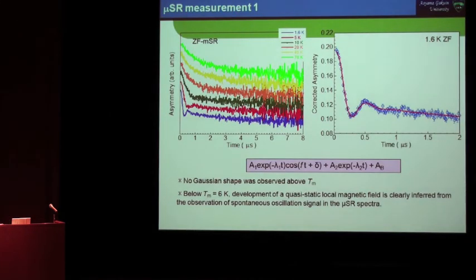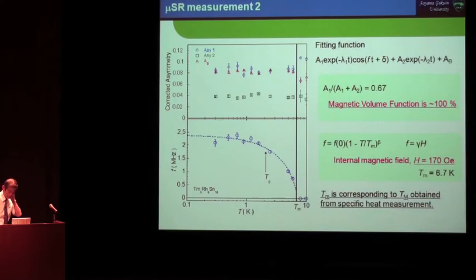So we tried to check the existence of magnetism. We tried to get a μSR measurement. This is one of the μSR measurements where we clearly observe the so-called oscillating behavior, suggesting that in some sense magnetism is existing. This is the frequency dependence here, and TC, TM is around here.